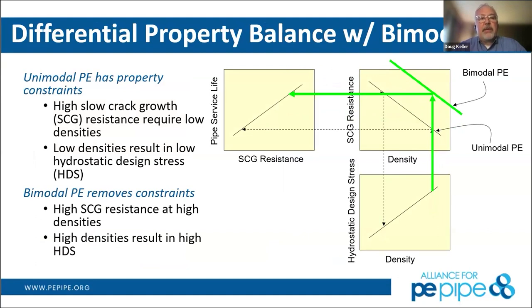So if we think about this from a cooking analogy, everything is in the same pot, which means that we have a relationship between the pipe service life and the slow crack growth resistance, which is the black line in the first diagram. Because we have that particular property set up, the slow crack growth resistance is a function of the density, and that's something that we have to balance with the hydrostatic design stress, or the ability to handle pressure. The lower the density, the less ability to handle pressure.